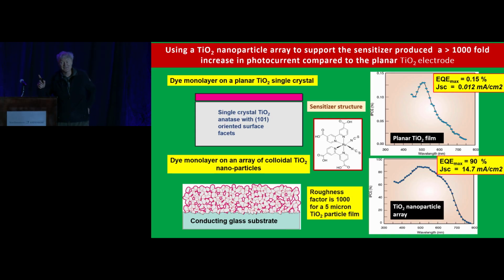I was traveling at that time to show our colleagues that these systems were real, and that you got those huge enhancements in photocurrent. You can see on the lower right side that now the quantum efficiencies are over 80%. That's practically quantitative conversion. All the photons in the spectral domain that hit the surface of this film will be converted to electric current with a molecular sensitizer.